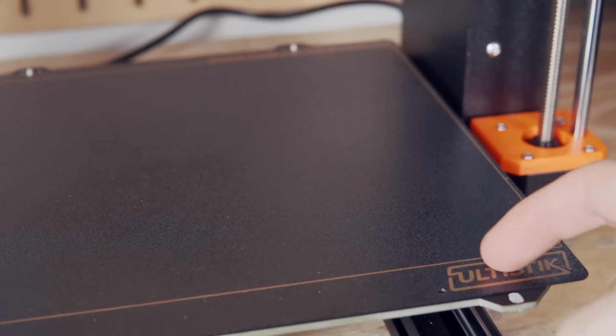For the bed, you will need a heated bed, which luckily has become a standard. That wasn't always the case. My temperature or sweet spot for printing with PETG is 70 Celsius, and my favorite bed surface for printing with PETG is powder coated PEI.